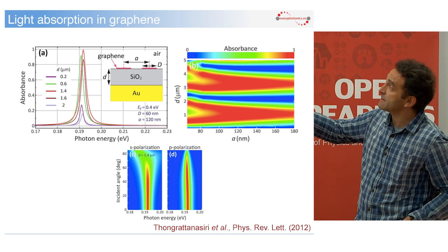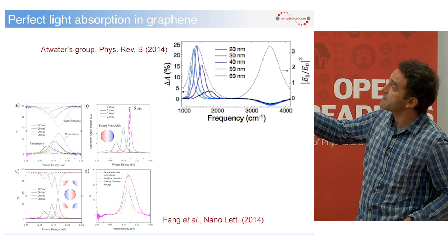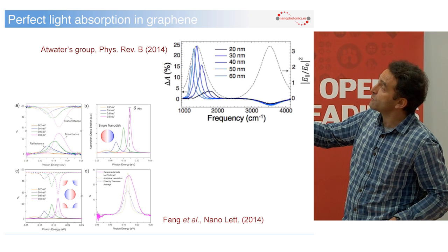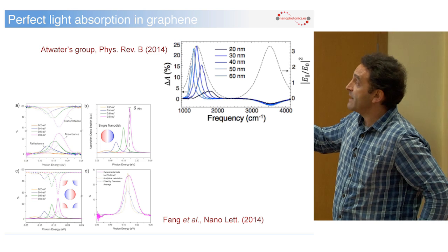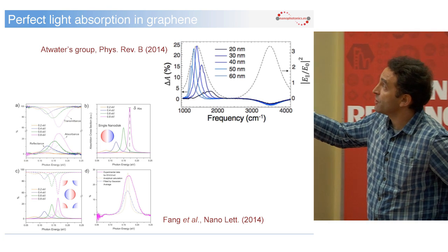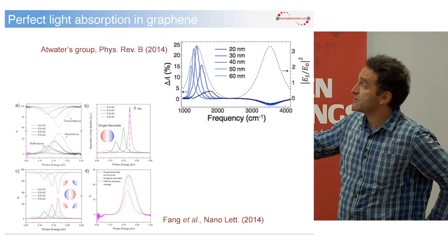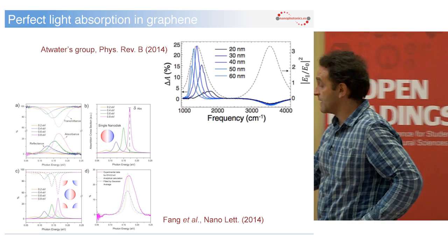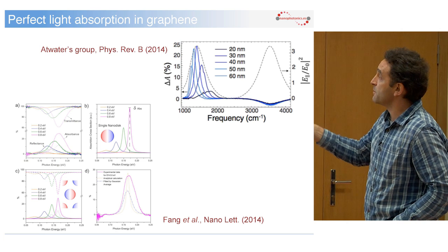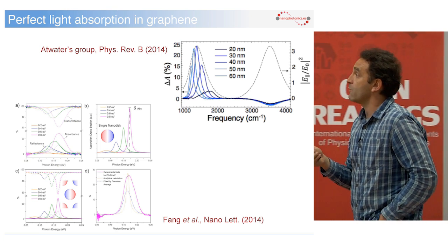And also because the dimensions, this size, are tens of nanometers compared to wavelengths that are microns, there is no phase associated with light propagation over these short distances. Therefore, the effect is omnidirectional. So it doesn't matter what the direction of the angle of incidence is for the light, it's going to have good absorption over a broad angular range.